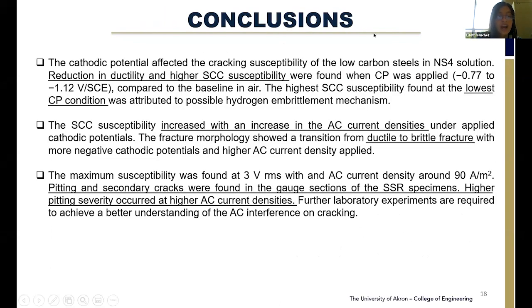So the conclusions that I have are, first, we know how the cathodic potential only, inside the solution, affects the ductility of the material and increases the cracking susceptibility. The highest susceptibility was found with the lowest cathodic potential and could be attributed to a hydrogen embrittlement mechanism. When the AC voltage is applied, we saw how the susceptibility increased with the AC current densities under the cathodic potential. Now, the result was different, and that depends on the cathodic potential applied.